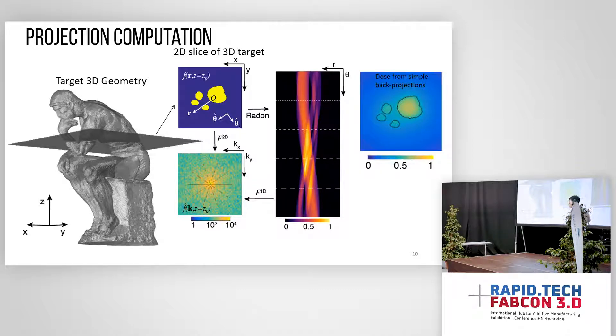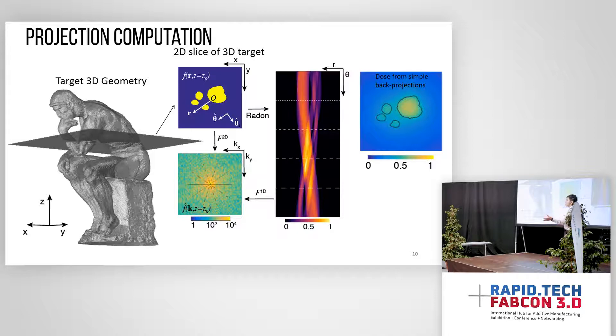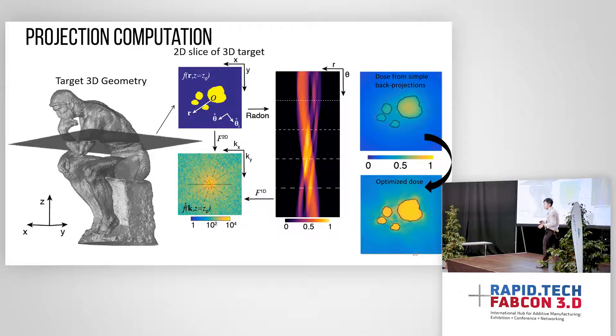But this synthesized image is not good enough — the contrast is really low because of an inherent limitation: we cannot project negative intensity. In computed tomography, you can use signal processing to achieve higher contrast, like Photoshop. But here we cannot project negative intensity, so we have to optimize the projections with what we have to get higher contrast at the end in the volume.